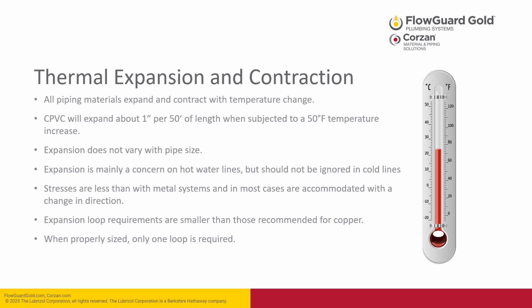All piping materials expand and contract with temperature change. CPVC will expand about 1 inch per 50 feet of length when subjected to a 50-degree temperature increase. The expansion does not vary with pipe size. Expansion is mainly a concern on hot water lines, but should not be ignored in cold lines. And the stresses are less than with metal systems, and in most cases can be accommodated with a simple change in direction. The expansion loop requirements are smaller than those recommended for copper. And when properly sized, only one loop is required.